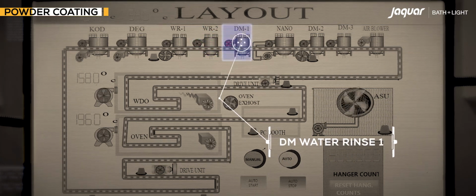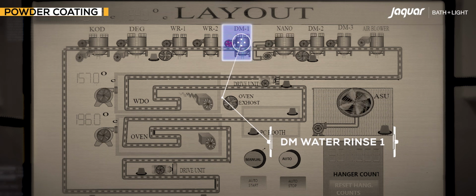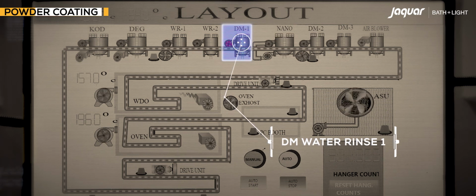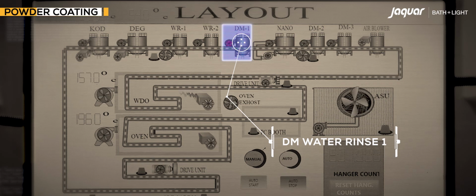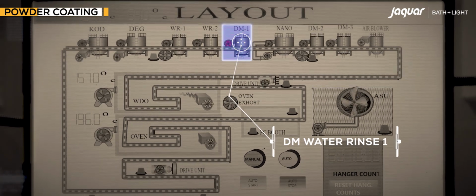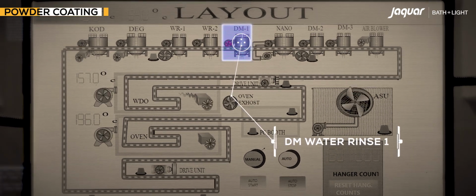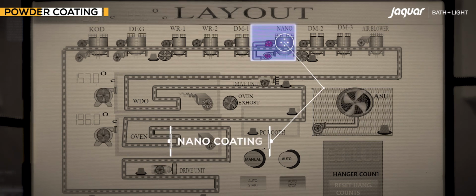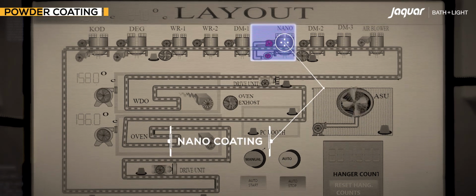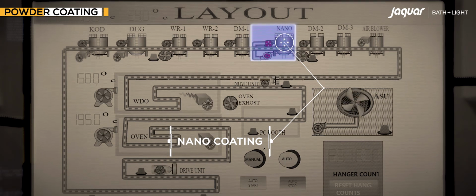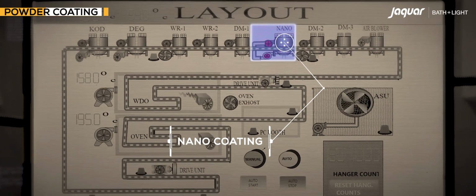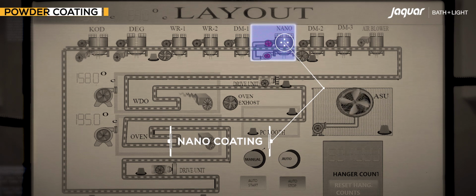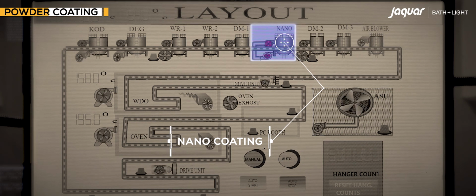Then, DM water rinse 1 takes place. The housing on the conveyor belt passes through a tank where demineralized water is sprayed to remove any iron residue to ensure that it will not get rusted. After that, nano coating is done. A special chemical is sprayed on it to make a thin film of up to 20 to 100 nanometers so that powder can stick to it homogeneously.